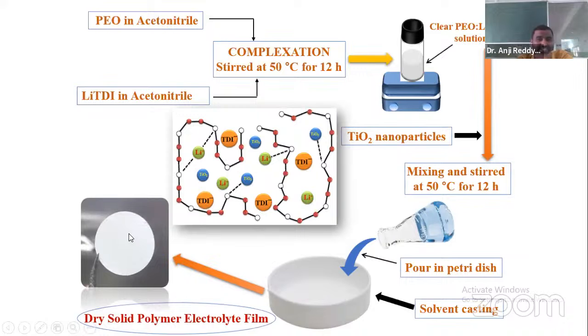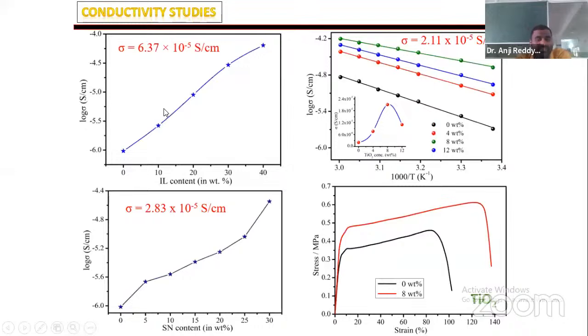Whatever film you are seeing here is with the TiO2. This is the polymer electrolyte with the TiO2. If you observe, as ionic liquid content increases, the conductivity increases. Here, as succinonitrile content increases, the conductivity increases. All are studied at 23 degrees centigrade. And this is the TiO2 content. By adding this ionic liquid at room temperature, 23 degrees centigrade, we achieve conductivity of the order of 10 to the power of minus 5, 6.37 into 10 to the power of minus 5. And with the succinonitrile, we achieve this conductivity at 23 degrees centigrade. And with the TiO2, we got this.